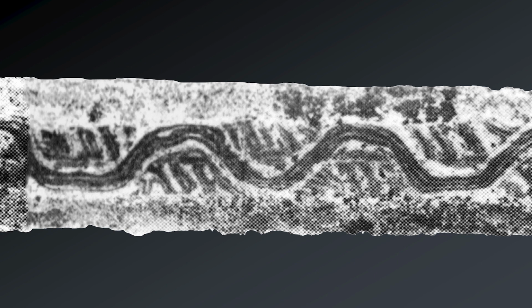Let me see if I can convince you of this. Let's remove the serpent inlay so that your eyes don't get distracted by it, and just look at the bars that remain. I see 3 bars. The outermost bars are made of a continuous twist to form sort of a chevron pattern with no change in direction. For those 2 bars, the grinding is shallow at about 10%. The central bar is harder to make out. Looks like a simple straight laminate with no twist and with the white layers being smaller or thinner. Something like this. Maybe. The problem with the central bar is that it's covered with the serpent most of its length, making it very hard to see. I also think it's possible that the central bar doesn't even have the outer white layers, or any white layers at all. At any rate, it is really hard to see.